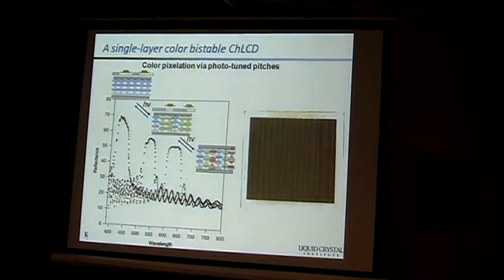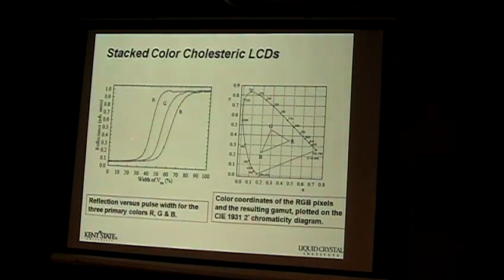This past May, at the Society for Information Display annual meeting in San Antonio, Texas, they showed one of the panels. So RGB has different kinds of response. Blue has a higher voltage, but anyway, for the earlier stacked colors you have this BGR, as I just mentioned, right? Blue has more chiral material and higher viscosity. The switching requires higher voltage, and red has less. For this encapsulation, it's not as good as it is right now.